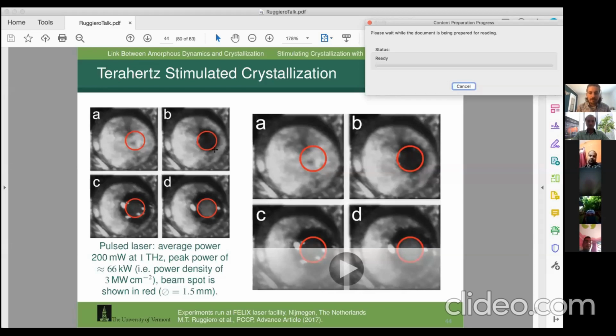What you see is that the terahertz is inducing a change in this amorphous solid, and that change is a disorder-to-order transition - it's actually crystallizing the drug inside this region. What's really cool is that when we heat the sample back up and let the outside crystallize normally, we get two different crystal structures, two different polymorphs.